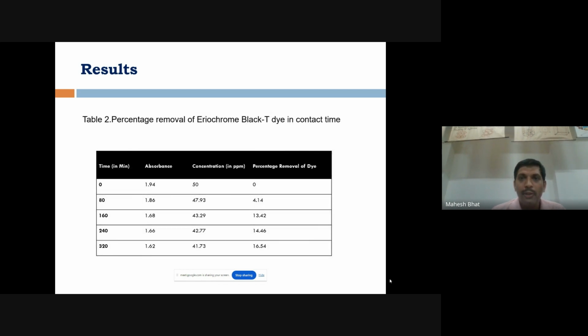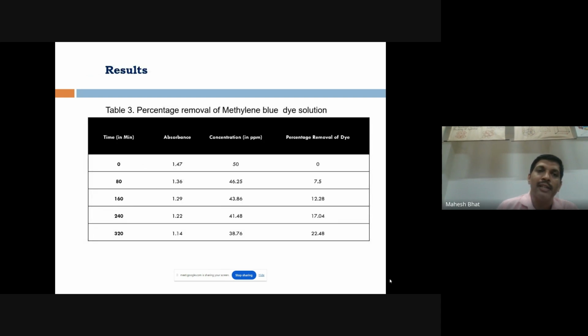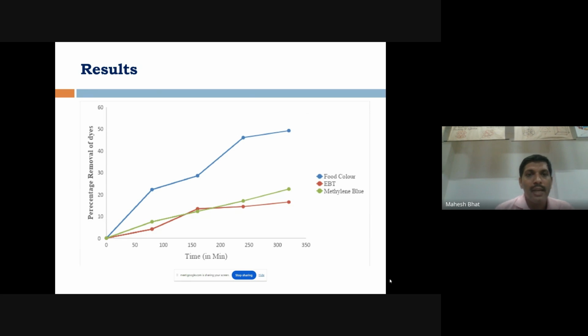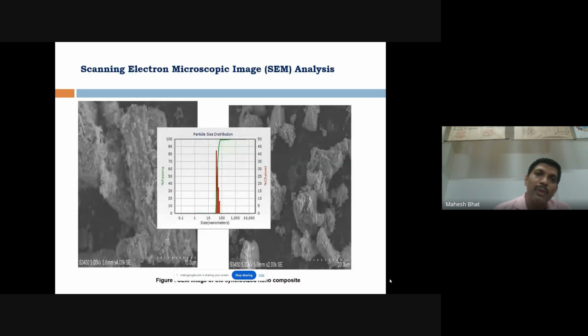In the case of the Eriochrome Black T dye solutions, the results show that there is a moderate removal of the color in a dye solution, about 16.54% removal of the dye. In the case of methylene blue, 22.48% of the color was removed. This graph shows the comparative study of three dyes, that is methylene blue, Eriochrome Black T, and the food color yellow. This shows that the efficient removal of food color yellow dye took place by the synthesized nanocomposite materials.